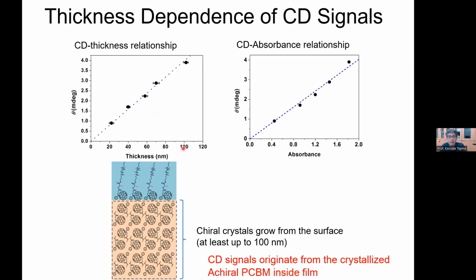So to check this, we change the thickness of this base film. By changing the concentration, you can change the film thickness, and you can see that this CD signal increases linearly with the film thickness. That means that this CD signal is coming from the bulk of the film, not the surface. So it's proved that this chiral crystallization is happening in the film.